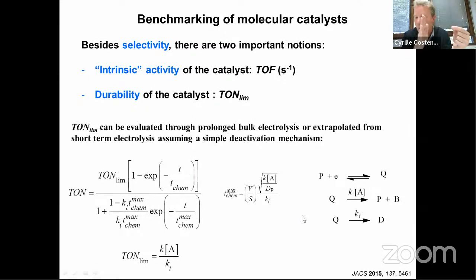And if the electron transport is not efficient enough, you will also have a diffusion reaction layer within your thick film. This is something that has been studied and observed in many systems where you have immobilization of the catalyst in a polymer, for example. If at some point you increase the size of your polymer, thinking that you will have more and more catalysts, so more and more current, actually you observe that at some point it levels off because you're not able to activate all the catalysts, because those which are away from your underlying electrode surface are not able to be activated by the electrons, I would say.